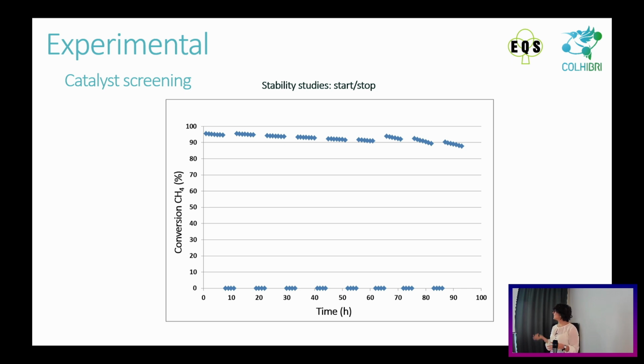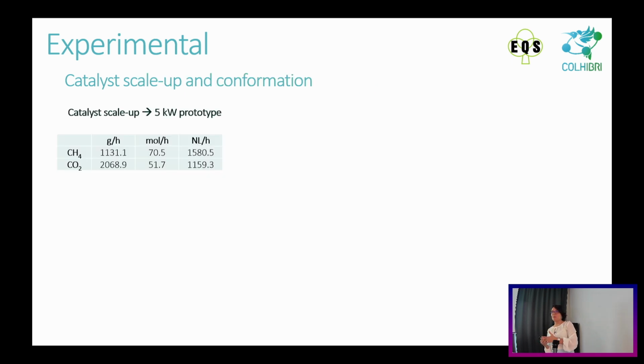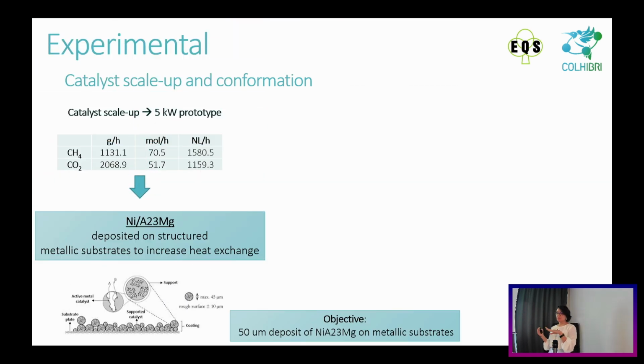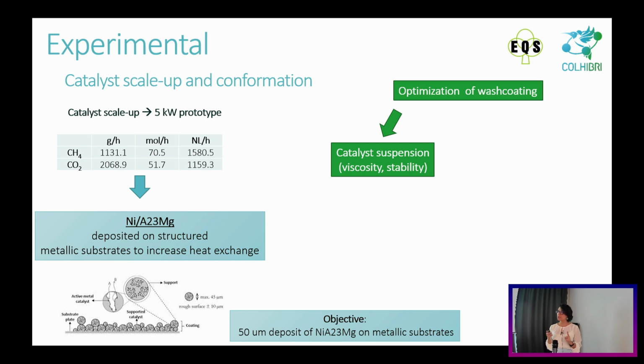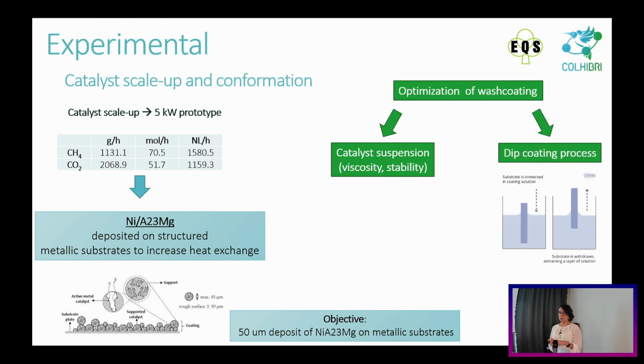And as you can see here, after 90 hours, we'll still have good stability of the catalyst. So then we move to the next step, which is the scale-up and conformation of this catalyst. What we want to do is to deposit the catalyst on the surface of metallic structures, and we're doing that through wash coating. So we need to optimize these parameters, which are the catalyst suspension and the dip coating process.